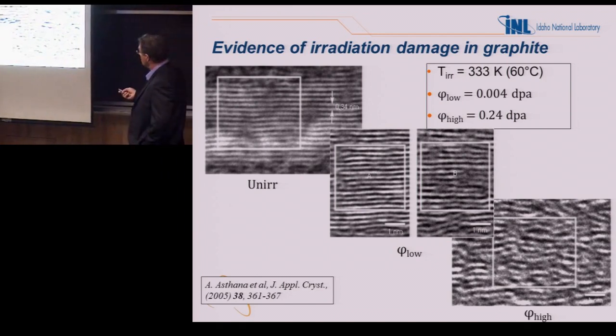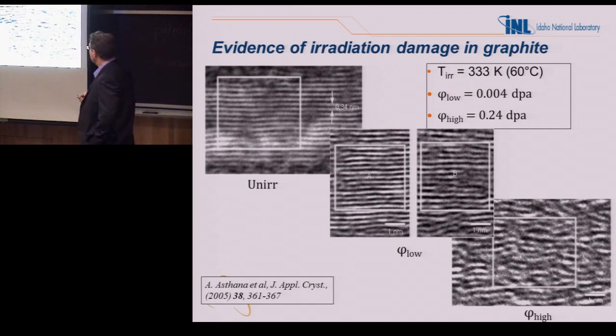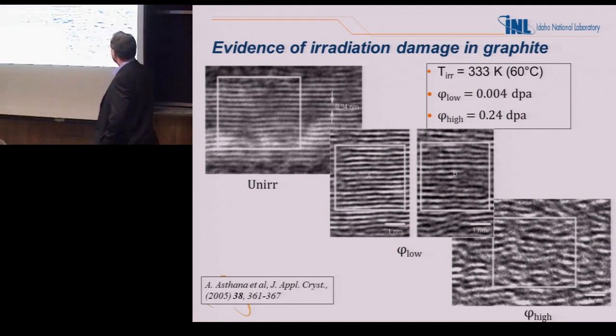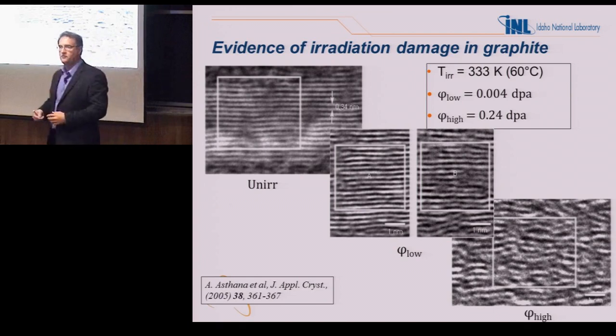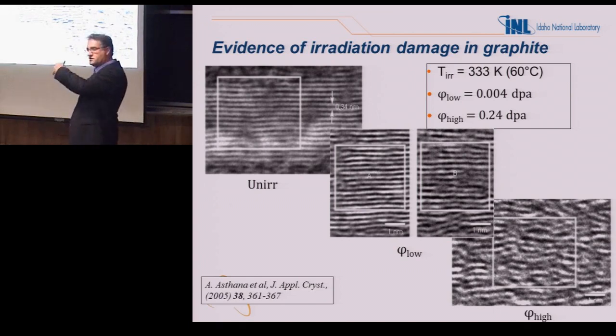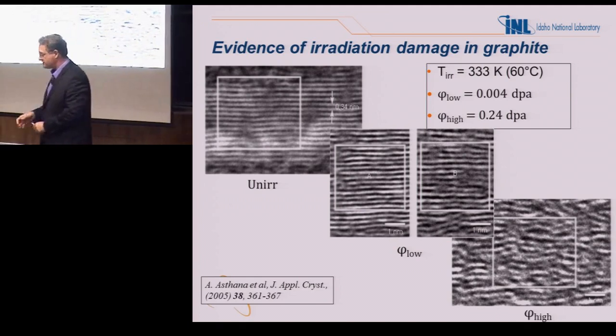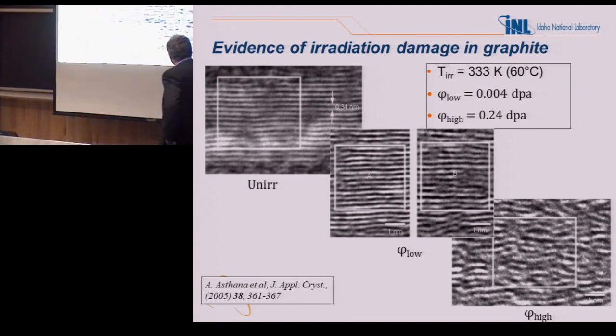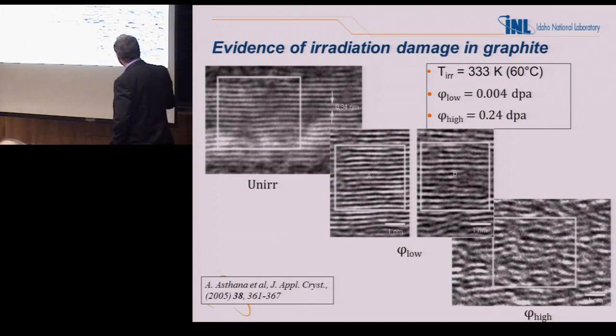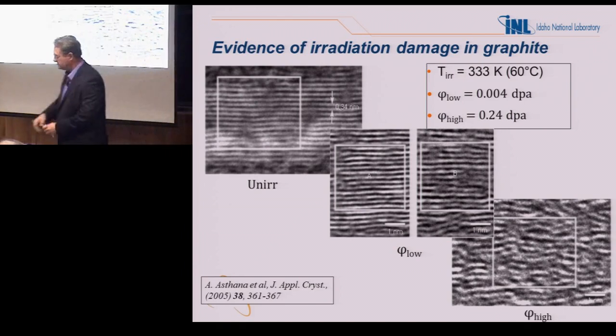Downhill stretch, guys. All right, so this is unirradiated. You see these nice planes in the high resolution TEM. A little bit of dose, very small. You still see the structure, but it's starting to get mixed up and disrupted. And then you get this sort of rucking, buckling type of process where it's literally starting to just destroy this beautiful page-like stack of graphene planes. And what's interesting is that they start to look like they're starting to interact with each other.